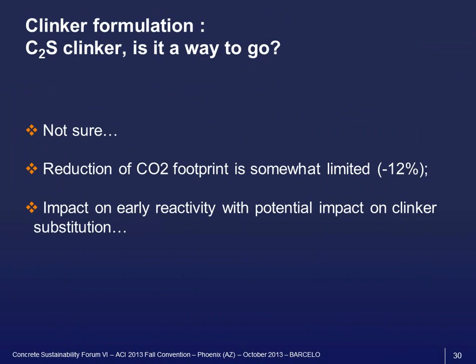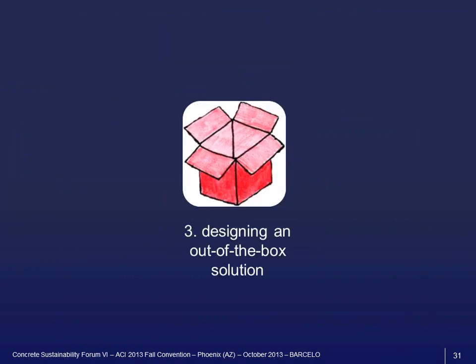So is it the way to go? I mean, we are not sure, because the CO2 footprint reduction is rather limited. It's 12%. We don't see that we have a very significant reduction amount in front of us. And the second aspect is that if we go that way, chances are that we are going to impact negatively the early reactivity of cement, and in consequence, we won't be able to use a lot of SCMs in cement.